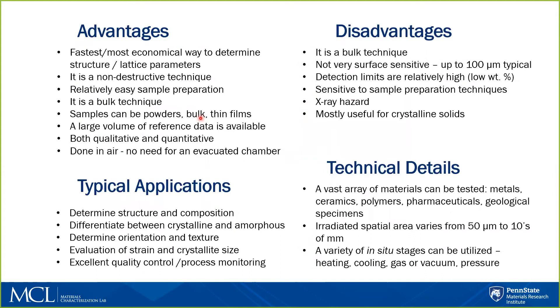The major advantages of the technique: it is a good way to get structure and lattice parameters, and it's probably the fastest and most economical way to do so. It is a non-destructive technique. The sample preparation is relatively simple in most cases. It is a bulk technique, which means that you're getting data that represents a rather large number of crystallites in the material, so it gives you an average of the material. Your samples can be in a variety of forms — powders, bulk samples, or thin films. There is a large volume of reference data available for comparison, and you get both qualitative and quantitative information in most cases, with experiments done in air, no need for any type of special evacuated chamber.